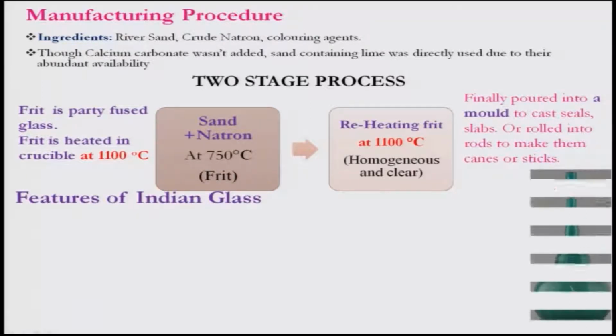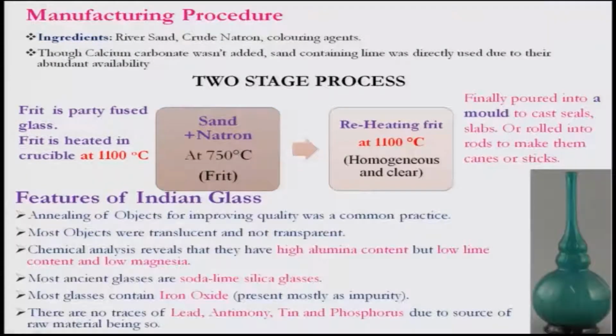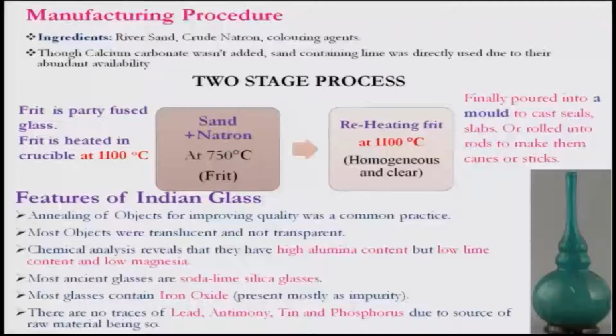As for the features of Indian glass, the annealing of the glass objects was carried out to improve the quality, and most of the objects were translucent, not transparent. Of course, later on transparent glass was made in the country, but in earlier days it was not. And chemical analysis reveals that they have a high alumina content, but low lime and low magnesium content.